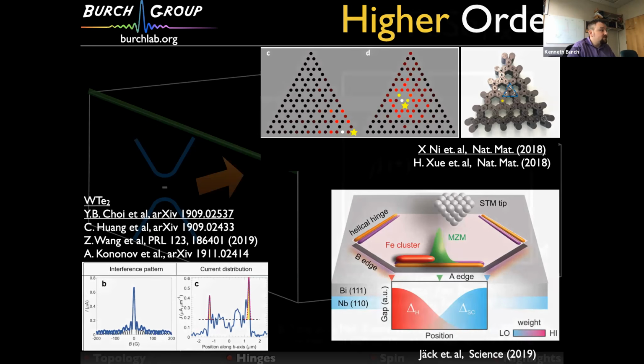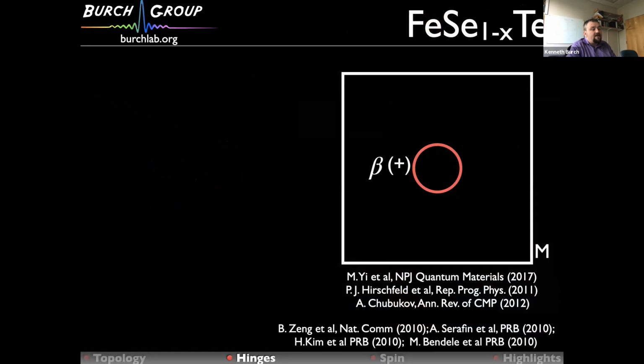Okay, so I want to tell you about how we have pursued this and why we chose to look at iron telluride selenide. So this requires taking a small step back for those who are less familiar with the iron-based systems. And just to remind you that these are systems where you have hole pockets at gamma and electron pockets at the corners at M.